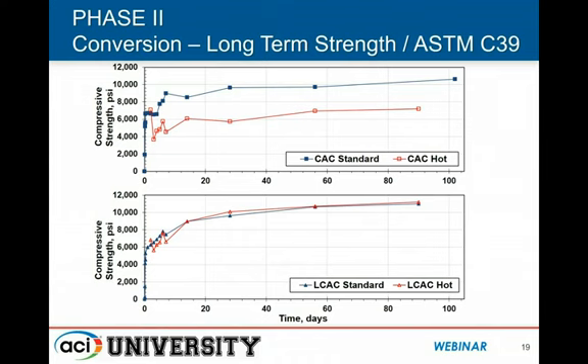So here's some results. What we were seeing in laboratory tests was closely reproduced after we took the material to the field and started employing it in actual construction. We saw very similar strength profiles, basically getting about 4,000 to 6,000 PSI in a few hours. So pretty amazing stuff. The strength takes off. And if you haven't worked with CACs before, they're impressive from that aspect, that you can get that early strength and then reliably get it. It comes in no matter what your early temperatures are. We found that in a lot of cases, the early temperature was not as significant.